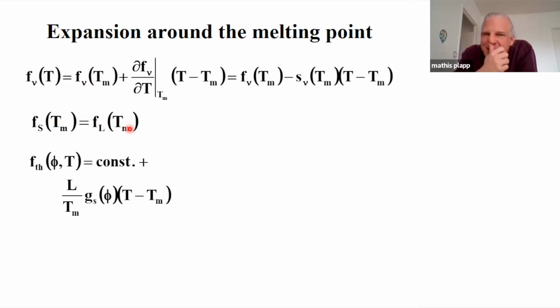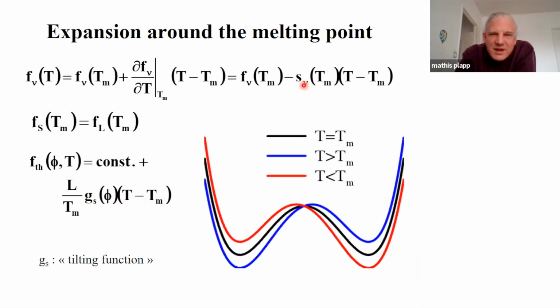That means that my thermodynamic part of the free energy is just a constant plus a contribution that is proportional to the difference of the temperature from the melting point, and that contains this interpolation function, this weight function G. And the coefficient contains the difference in entropy density between the solid and the liquid, and this is nothing but the latent heat. And this gives you another interpretation of this weight function, because it is often called a tilting function.